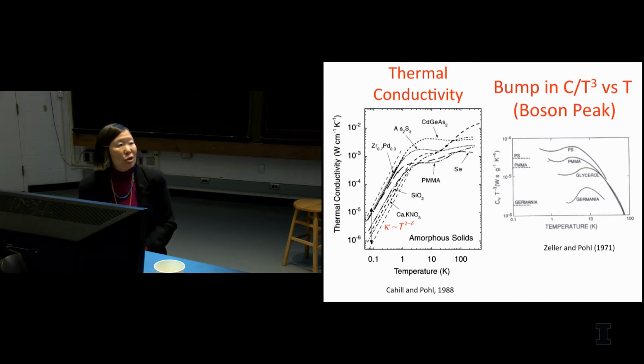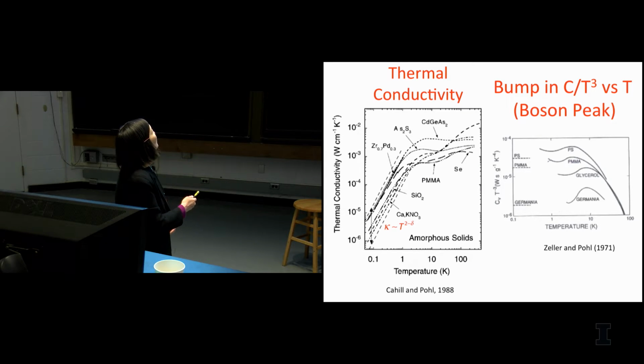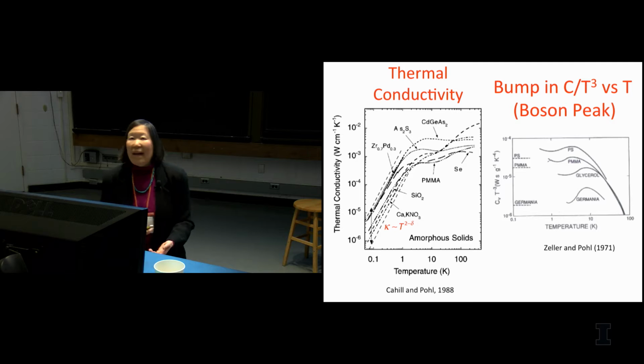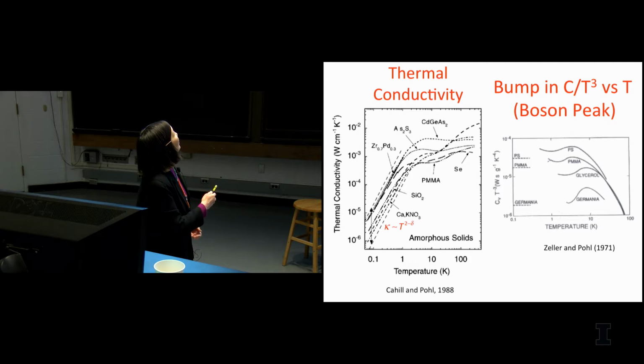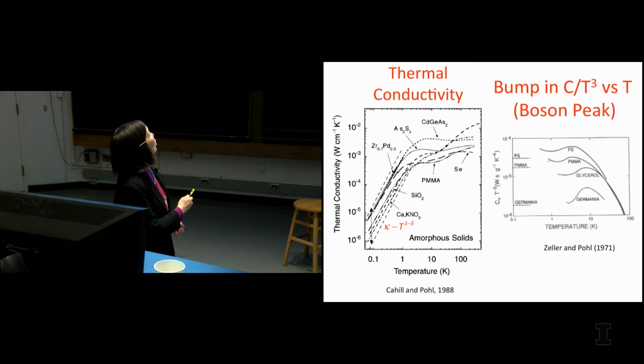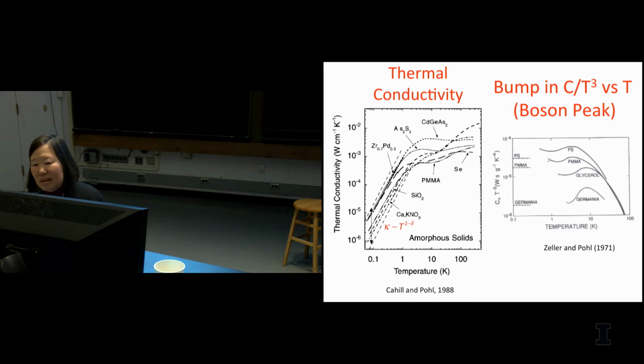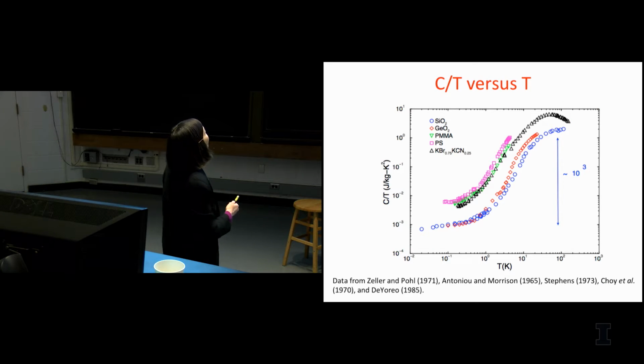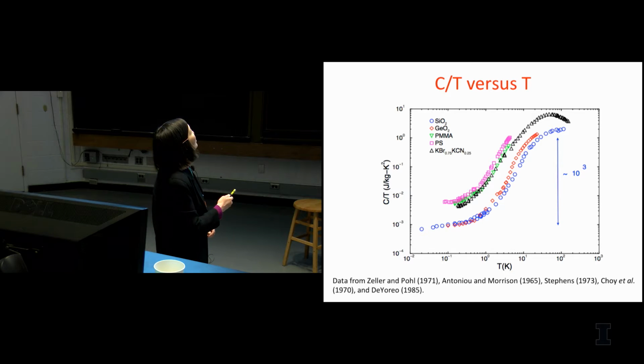If you look in that region at the thermal conductivity, here's thermal conductivity versus temperature in a log-log plot, you get T squared, and actually it's subquadratic, T to the 1.8. And then between 3 and 10 Kelvin, you get a plateau in the thermal conductivity, and the thermal conductivity rises above that. In that region where there's a plateau, if you look at specific heat divided by T cubed versus T on a log-log plot, you get this bump in C over T cubed, sometimes referred to nowadays as the boson peak. I like to plot C over T versus temperature in a log-log plot, and there you see this rise in C over T between 1 and 10 Kelvin.